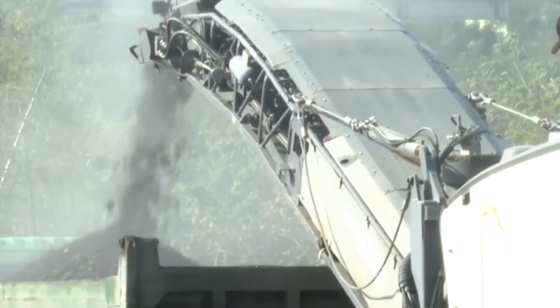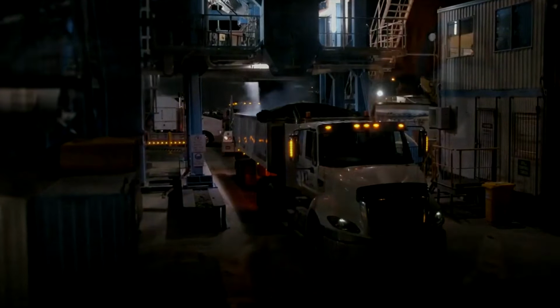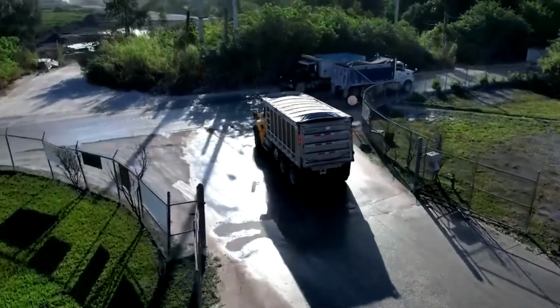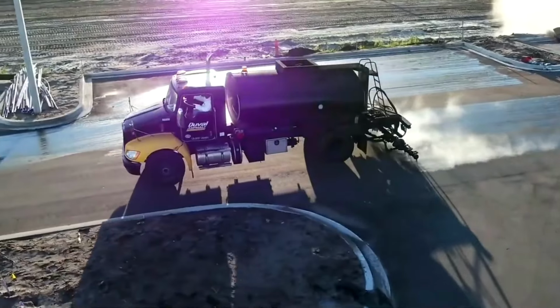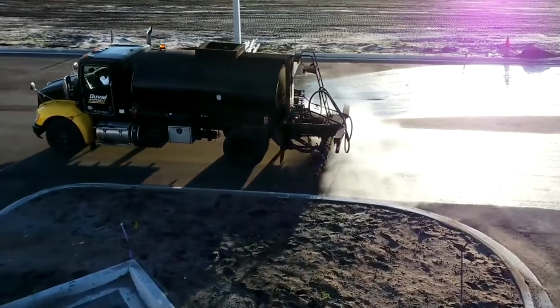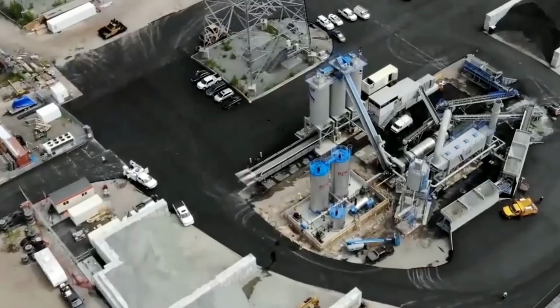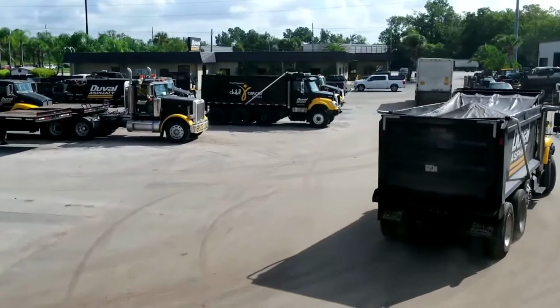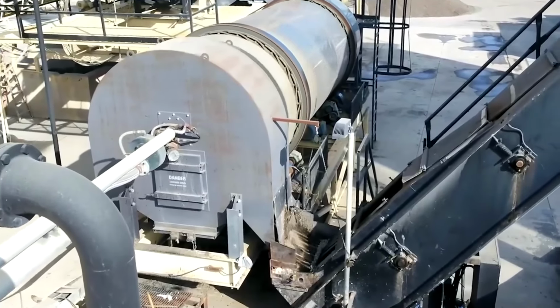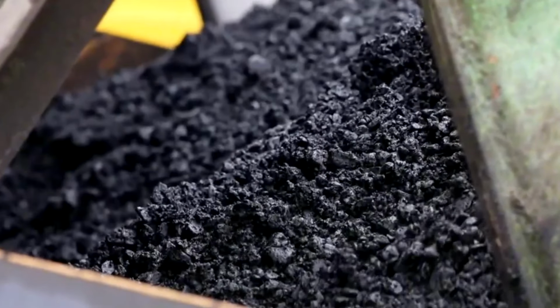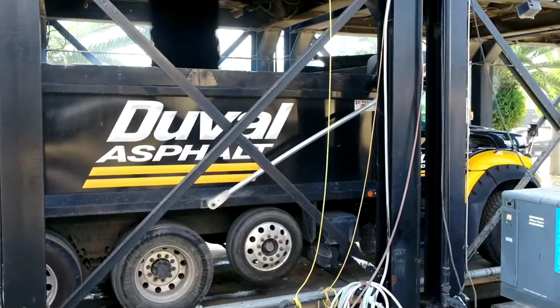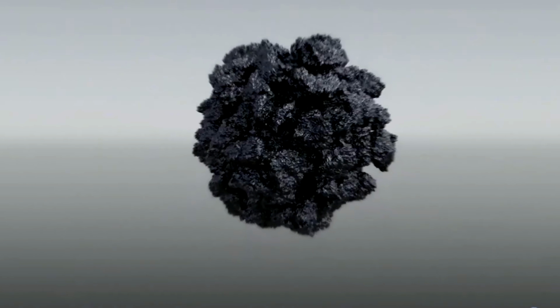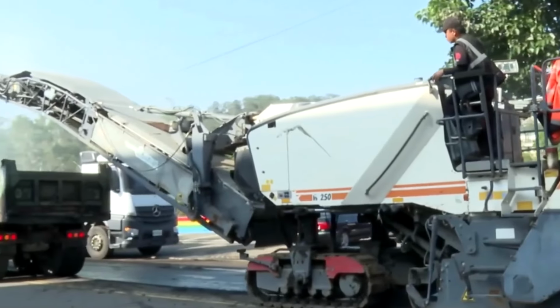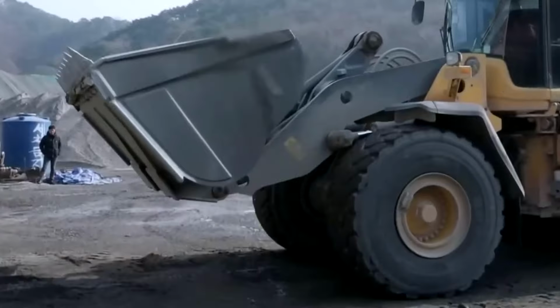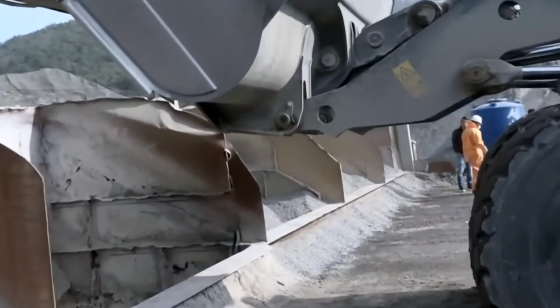Immediately after placement, the compaction phase begins. Steel vibratory rollers provide the initial finish, while pneumatic tire rollers seal the internal air voids. The entire sequence is calculated to finish before the mixture cools below 180 degrees Fahrenheit. Below this threshold, the binder loses its optimal capability to bond the aggregate, compromising the road's integrity. Compaction machinery moves continuously to ensure the density meets engineering standards. Thus, the recycled tires officially become an integral part of the road infrastructure, ready to serve for years.